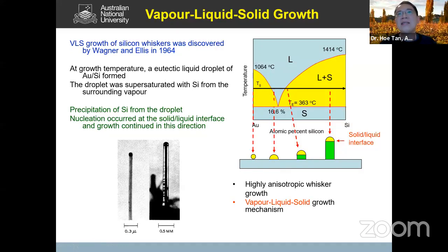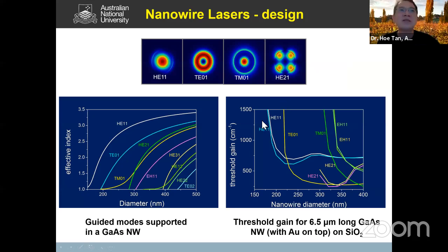We can get these nanoparticles very easily these days. You can buy them off the shelf, in all sorts of shapes and sizes, ranging from about 10 nanometers all the way to a few hundred nanometers. But before we make lasers with these nanowires, we need to think about what is the optimum diameter. So we've calculated the effective refractive index as a function of diameter.